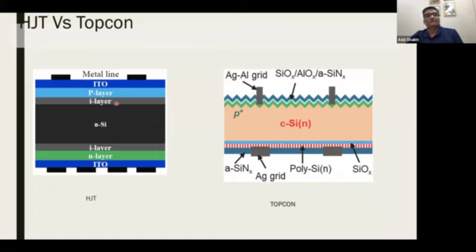Okay, very thin. It is 5 nanometers. So through that the carrier can tunnel through. Okay. Thank you. And this is an amorphous doped hydrogenated silicon, which combined with the N-type wafer does form a junction. Okay, and you need an ITO here because you need to have transfer. I mean, this acts as an anti-reflective coating as well as lateral transfer of the carriers. Okay, for both of them.